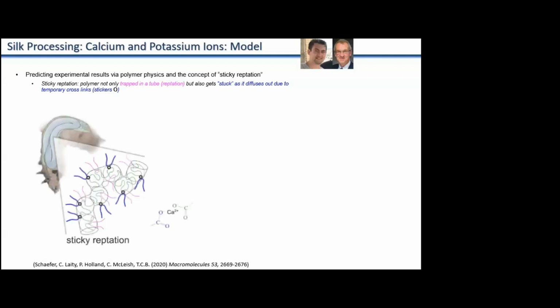But the idea is that these silk proteins have carboxylate groups on them, where basically your oxygen atoms between two chains can be bridged with calcium as a salt. So calcium is a divalent metal ion, so it can make a divalent metal ion bridge between two chains. A bridge between two chains is molecular friction. Viscosity is friction caused in terms of the amount of force required for chains to move over each other. So throughout the silk's sequence are sticky points called stickers, and the calcium bridges between those sticky points increase the friction inside the gel, which will increase its viscosity.